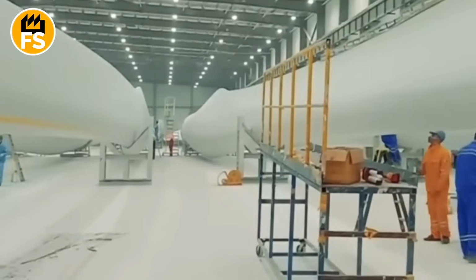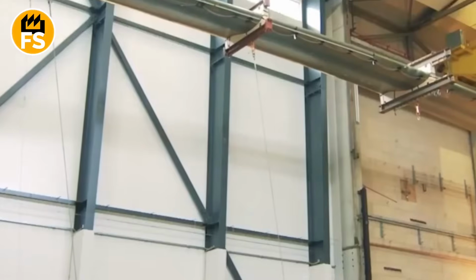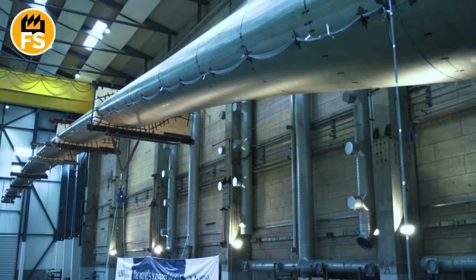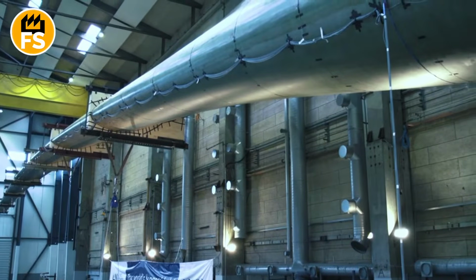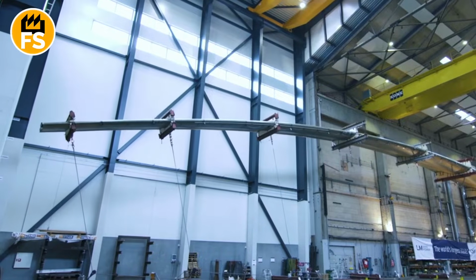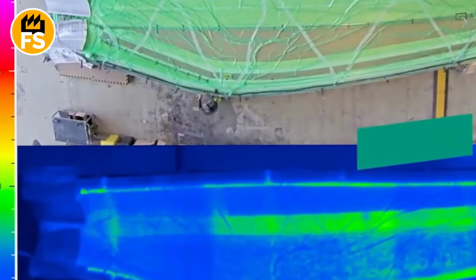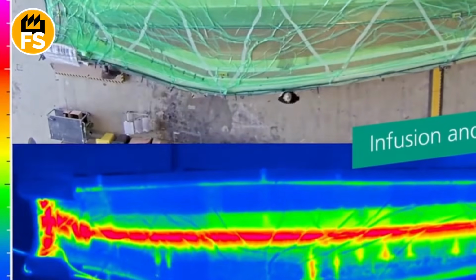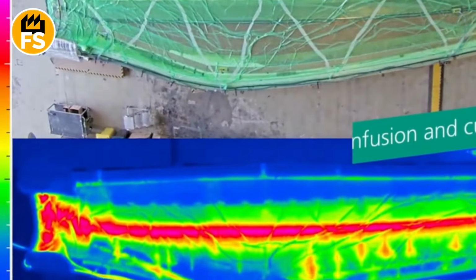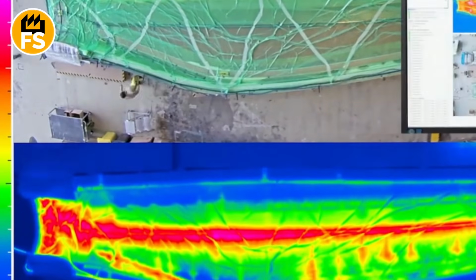No blade leaves the factory without thorough inspection, since internal defects like air pockets or poor resin impregnation can lead to catastrophic failure. Ultrasonic scanning detects internal defects, voids, and composite delamination. Thermography measures thermal signatures to identify areas with varying density, such as defective bonding.